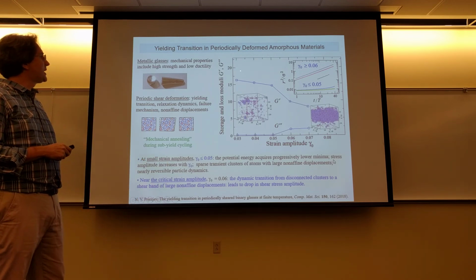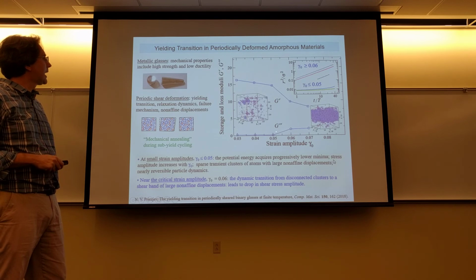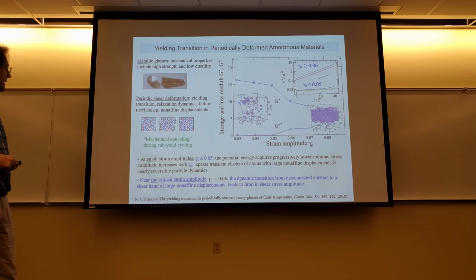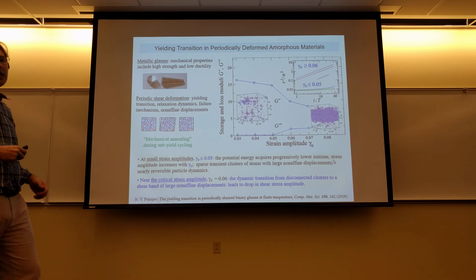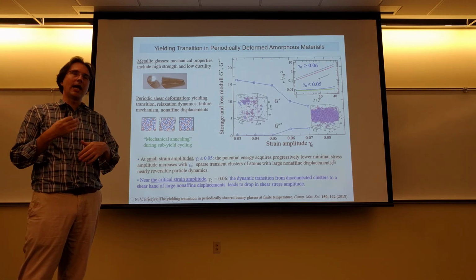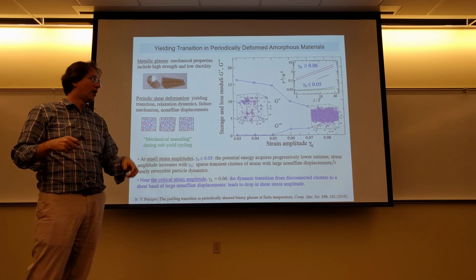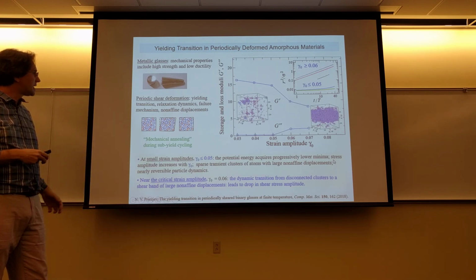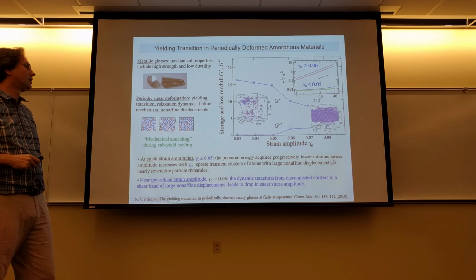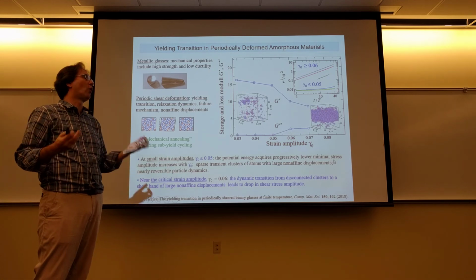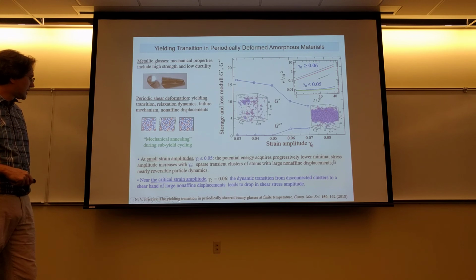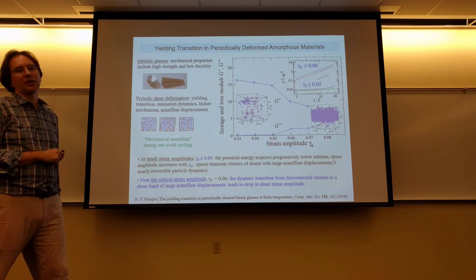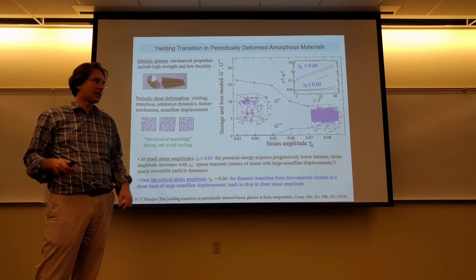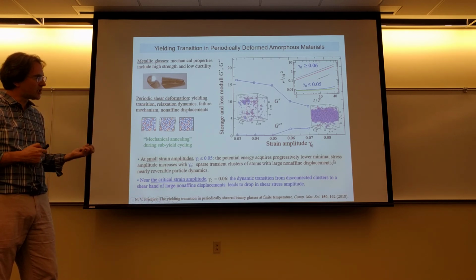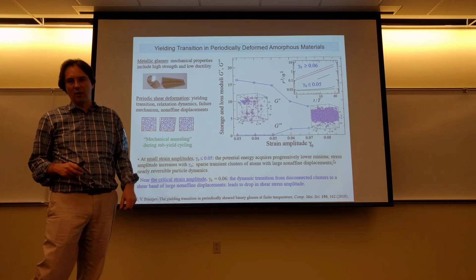What's interesting here is that in the elastic regime one can view this sub-yield cycling as some sort of mechanical annealing, where over consecutive cycling the energy of the material is reduced, and it becomes more dense and more brittle. This is one example of how you can process material, and the details of this research can be found in the following paper. But overall, in the last 5 years, I wrote about 20 papers on this topic, which can all be found on my webpage.